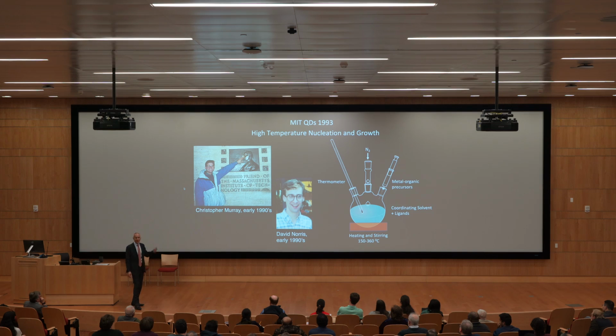And this is our simple flask. Now it's called the hot injection method. We have organometallic precursors that are stable at room temperature, in a solution of a solvent. We quickly inject that into a coordinating solvent with some ligands that coordinate to the surface of this crystal as it grows to prevent it from growing too fast. Kind of like the idea that LaMer had to go to a really low temperature to prevent the particle from growing too fast.